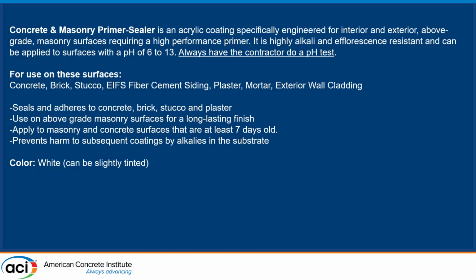And I always recommend your specifications for that contractor to do a pH test. I know me and Mark were both commercial reps in the field, and everybody's looking around, well, who pays for that? Who does this? And as architects, specifiers, and manufacturers, we're not third-party inspectors, but we will go out there and assist the contractor with a pH test. I always required, when I would do one, I'd like the GC to be present, maybe an architect, not necessarily an owner, but I like to have more than 2 or 3 people out there to witness the pH test. And the contractor should, it's their due diligence responsibility to make sure that pH is low enough before they start top coating and priming that tilt wall.